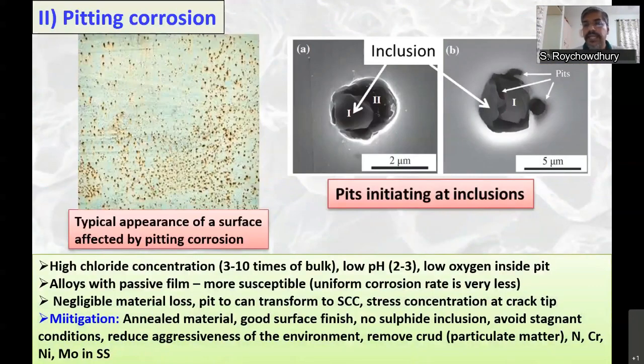But when you use highly alloyed materials like stainless steel, uniform corrosion is not a problem. The uniform corrosion rate for stainless steel, say in a chloride containing environment, will be very low, around 1 to 5 mils per year, but they will undergo very severe localized corrosion like pitting corrosion. A surface affected by pitting corrosion will look like this. These small dots are nothing but holes. It's like drilling a hole through the thickness, and this is a higher magnification. The preferred locations of initiation are the inclusions. When inclusions are present, they are the preferred location for pit initiation.